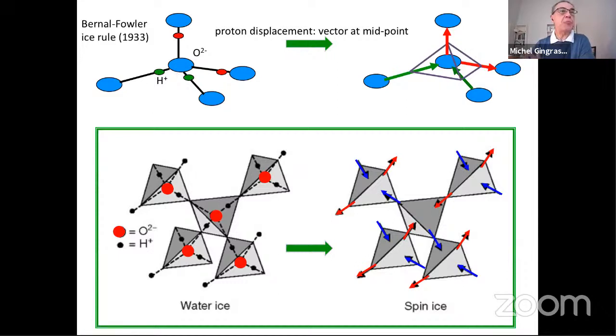And so one can represent that configuration by vector displacement. We can locate the center of the bond between two neighboring oxygen, and ask in what direction the proton on that bond is displaced. So for example, this proton here is displaced from the midpoint towards this oxygen, represented here by the green arrow. And so you see where I'm going with this. These two protons here are pointing towards this centered oxygen, whereas these two protons here are displaced with respect to the midpoint towards these two oxygen. And so the local configuration of protons near reference oxygens, which is two protons near, two protons far, maps directly into two vectors pointing in and two vectors pointing out.